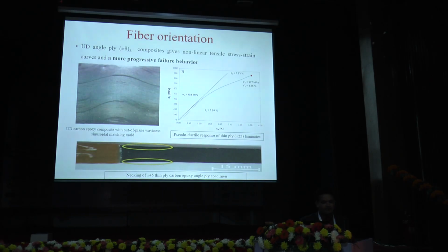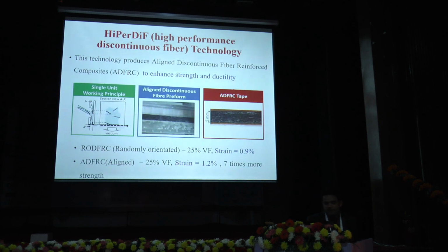Fiber orientation or ply orientation gives a more non-linear tensile stress-strain curve and more progressive failure behavior. This is the technique to use high performance discontinuous fiber in aligned form, and you can see that percentage strain is increased if the fibers are aligned as compared to random orientation.